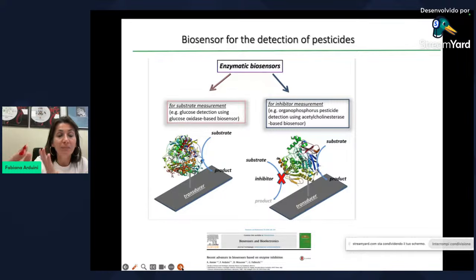So we need to make the measurement in the absence of the inhibitor, meaning the response of the biosensor, and in the presence of the inhibitor. And if we observe a decrease of the response, it means that the inhibitor is present in the sample. This type of inhibition biosensor, for example, is used for detection of organophosphorus and carbamate pesticides, which are inhibitors of the cholinesterase enzyme.